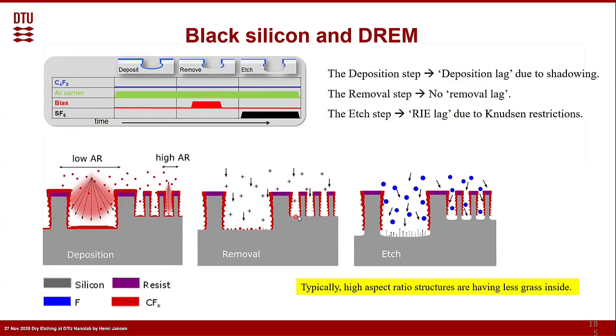It means that the smaller structures tend to be already free from this fluorocarbon in the earlier states than the big ones. If you then stop a little bit too early, then this one can be already clean, but this one is still there. There's still some fluorocarbon. If you then continue, that will be our, let's say, nanograss, micrograss, whatever you call it, and creates these pillars or black silicon. That means at the big open structures, you will start to develop grass, whereas in the smaller ones, it's not.